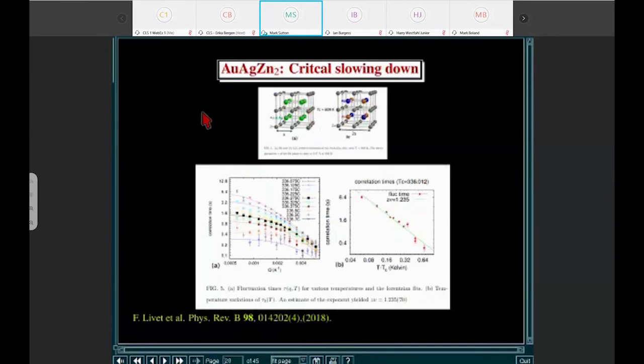And one of the problems I've been working on a long time is, can we see critical slowing down near a first-order phase transition? And here's an example showing that in a Heusler-like alloy, where the ordering of the gold and the silver is a continuous phase transition. It has a lot of the properties of an Ising model, and we can measure the time constant as a function of angle and as a function of temperature as we follow it, and measure the critical exponent of how the ordering happens, and that's described here.